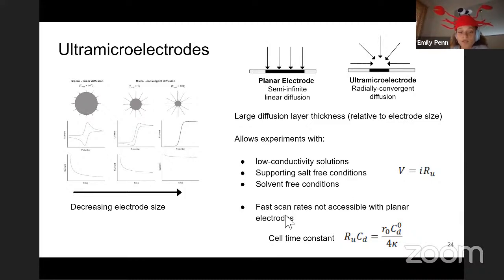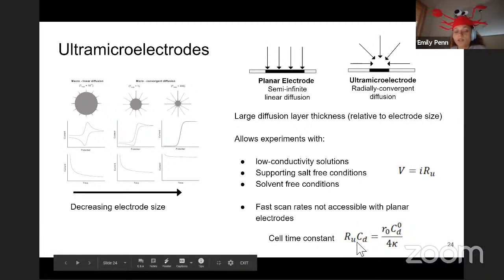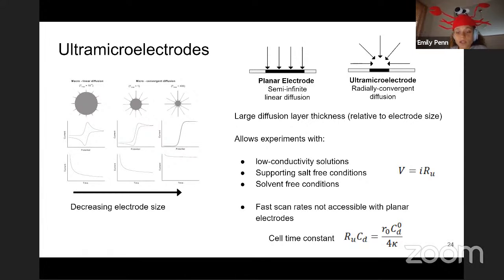Also, we're able to scan at fast scan rates that are not typically accessible with larger planar electrodes. How fast of a scan you can do in a CV is related to the cell time constant, which is the uncompensated resistance times the capacitance. So this is a function of the electrode radius. If our electrode radius is really small, then this gives us a lower cell time constant. Since our cell time constant is smaller, we're able to scan at faster scan rates.